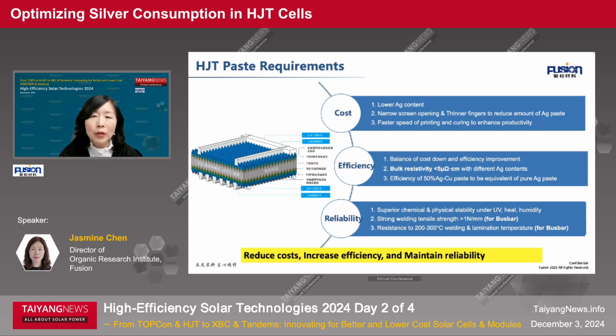The cell manufacturers now use several approaches for cost reduction. They use a narrow screen opening and thinner fingers to reduce the amount of silver, and also use faster printing and curing speeds to enhance production. They also place high demands on us, and we need to provide lower and lower silver content to reduce the cost. But even with cost reduction, we cannot compromise efficiency and performance. From the efficiency side, we need to balance cost down with efficiency improvement.